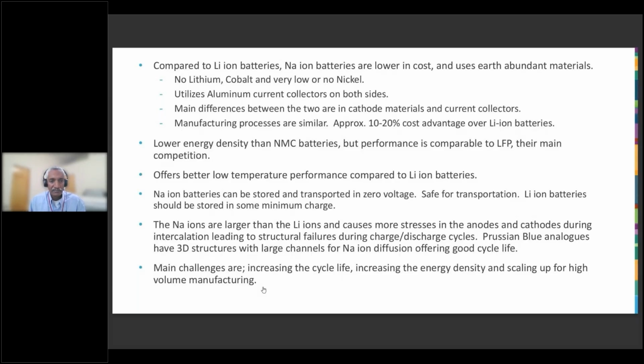As I discussed a little bit earlier, sodium ions are larger than lithium ions. It puts more stress in the anode and cathode during intercalation, leading to structural failures during charge and discharge. So cycle life is one of the important criteria. Except Prussian blue analogs, they have a good cycle life. The main challenges with sodium-ion batteries are increasing the cycle life, increasing the energy density, and scaling up for high volume manufacturing, which you're going to hear a little bit more from Natron. That's all I have. Thank you for listening. I'll pass on to the next speaker, Alex.